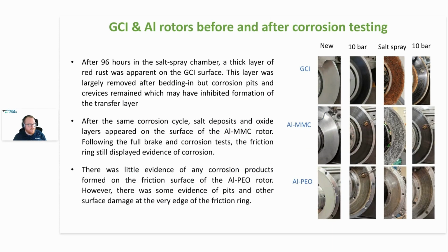The mixed metal composite rotor in the center also shows salt deposits after the corrosion cycle, and again, the deposits are largely removed during the subsequent braking, but evidence of surface damage remained. Finally, the PEO-coated aluminium rotor shows very little effects of corrosion, and a transfer layer was very quickly reestablished on its rubbing surface.